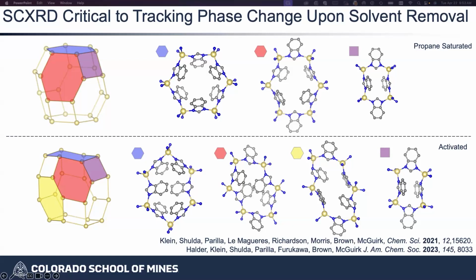And so when this system shows that type of adsorption, what you're basically doing is going from this state. There's some energy threshold that has to be overcome by the concentration of the gas, and it goes to this more open state. We've done a lot of in situ studies looking at this more specifically, but I just have to summarize that here. By using the crystallography, we were able to infer what was the Velcro that closed the system. And because hydrogen couldn't open it, we needed to weaken the Velcro. And so we could see that there was pretty clearly CH-pi stacking or CH-pi interactions going on here.